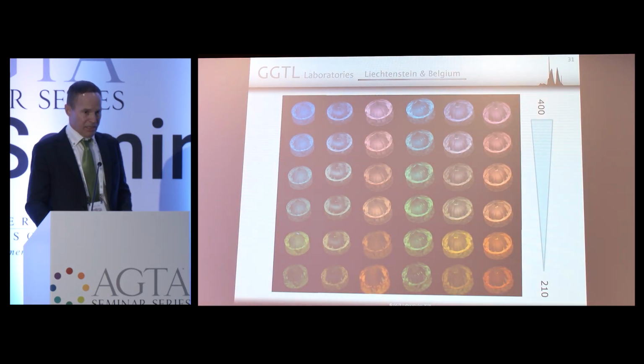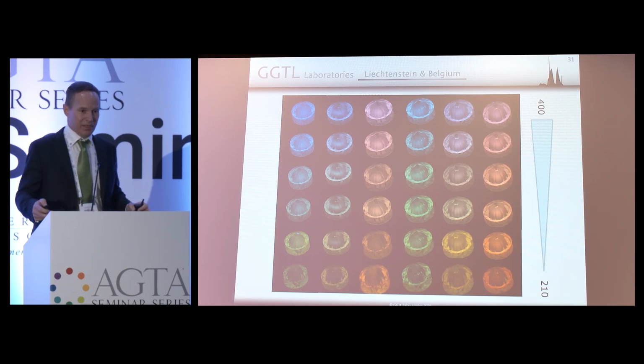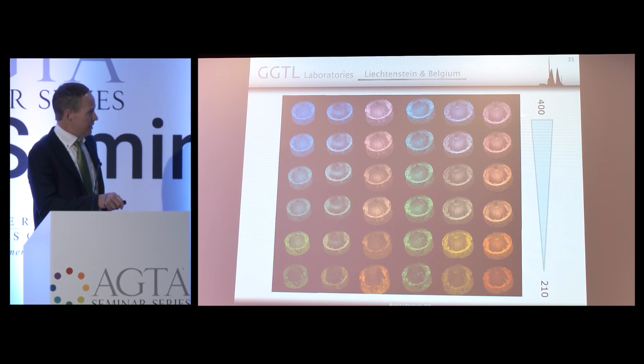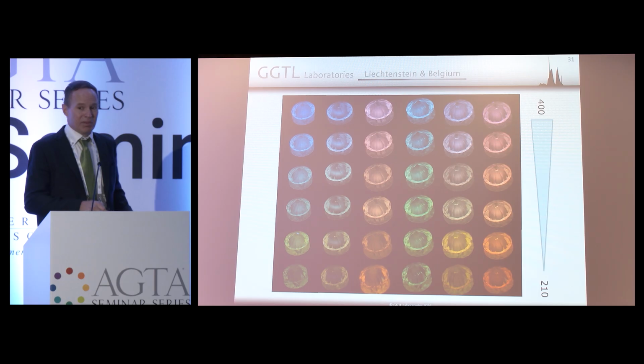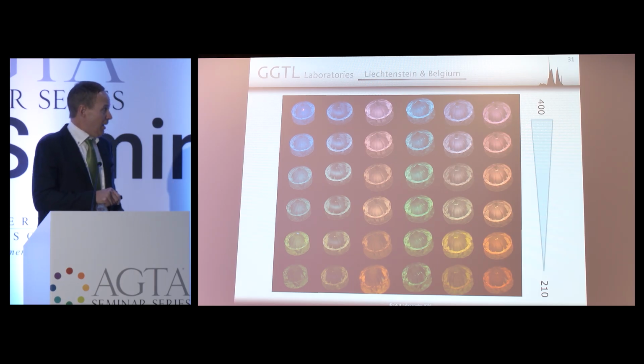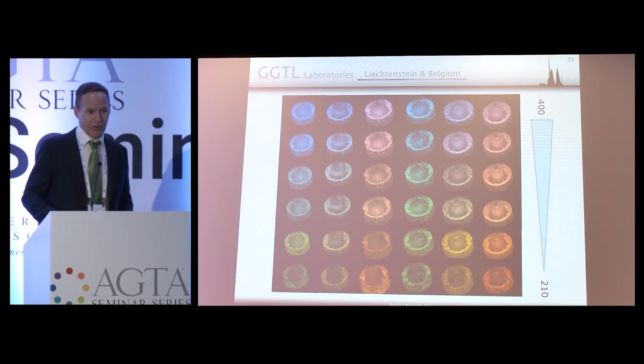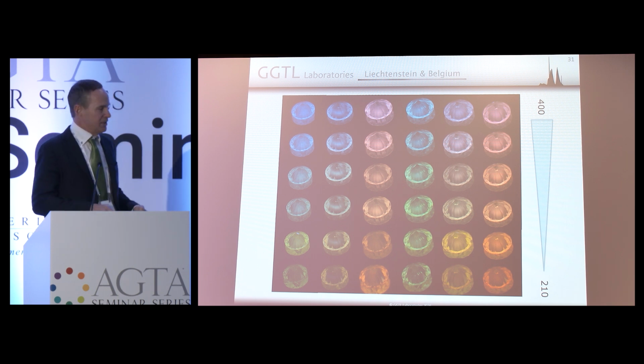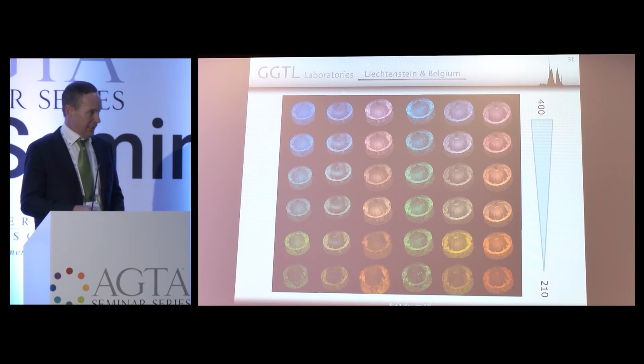And here, an example that shows you how wide it can vary. So here we're at long wave excitation, and here we're at deep UV. So long wave, you can see, I mean, this stone fluoresces blue. So anybody tells you, oh, blue fluorescence doesn't exist for synthetics, it absolutely does. But, as I mentioned before, this fluorescence that you see here, if you take a regular long-wave UV lamp, it'll probably show as inert or faint, very faint blue. Okay, this is under a DFI, so it's high-power UV. That's why it's visible. But otherwise, it will be a very faint fluorescence.